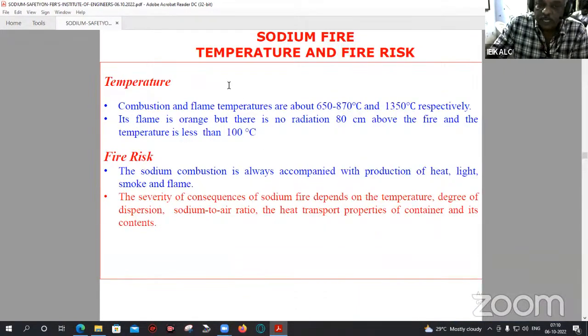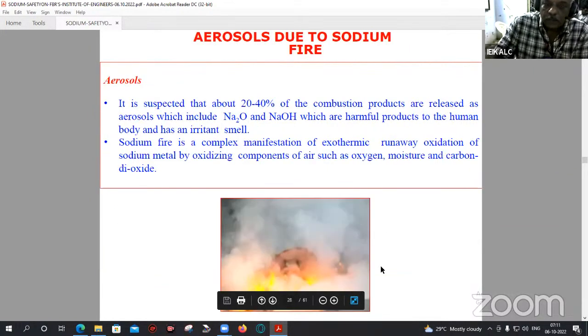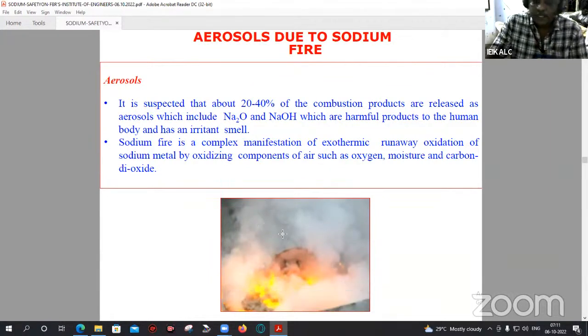Combustion and flame temperatures: suppose there is a sodium fire, the temperatures may be of the order of 650 to 870 degrees centigrade, right on top of the pool. And it does not radiate much, because personnel can approach very near to the sodium fire and extinguish it. Sodium combustion always produces heat, light, smoke, and flame. The severity of consequence depends on the temperature, degree of dispersion, sodium to air ratio, heat transport properties, and its contents. You can see the white dense aerosol, and this contains sodium oxide, sodium hydroxide, sodium carbonate. When it goes above, it becomes sodium carbonate, highly irritating in smell. It can affect our eyes, throat, etc.